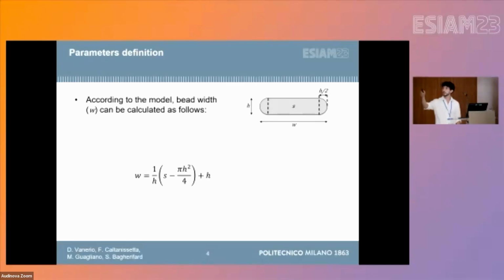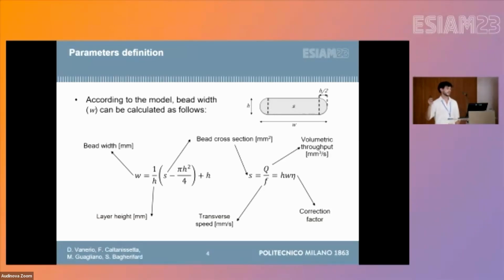We have this simple geometrical formula for the width. The geometry is basically a rectangle with 2 semicircles at the extremities. In the formula, you see the bead width, the layer height, and the bead cross section. The bead cross-section can be calculated as the ratio between the volumetric throughput and the transverse speed of the robot. It can also be calculated as the product of the width, the height, and a correction factor, which corrects according to the semicircular shape at the extremities.